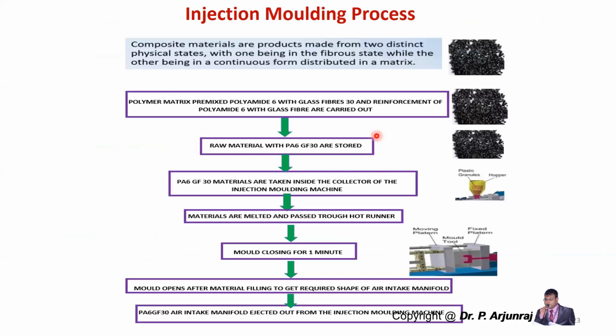And this is the injection molding process. The composite materials are products which are made up of distinct physical states, one being in the fiber state, while the other is distributed in a matrix form. In the first stage, the polymer matrix is pre-mixed, where the polyamide PA6 and glass fiber of 30% are mixed, and the reinforcement of PA6 with glass fiber 30% is carried out.